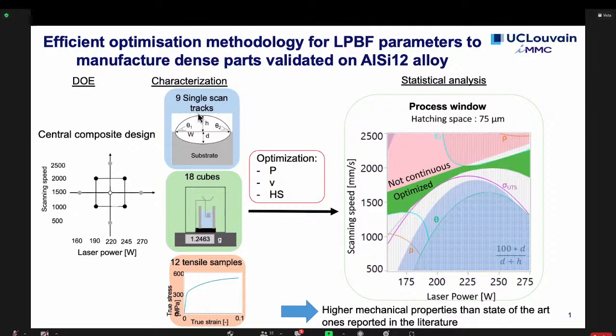Then the methodology is divided into three parts. First we manufactured single scan tracks, because if we suppose that a part is made of the overlapping of single scan tracks, then the properties of the part will depend on the properties of each single track. For that, we analyzed if the track is continuous to avoid porosity. We checked that there is enough penetration to have good cohesion between the new layer and the previous one. We also look at the height in order to build the height of the part efficiently, and at the contact angle, which should be close to 90 degrees in order to have good manufacturing accuracy.